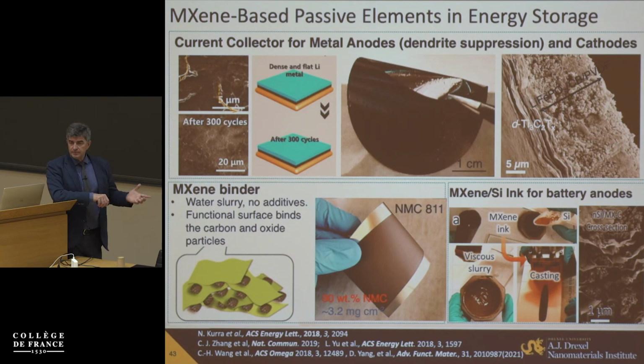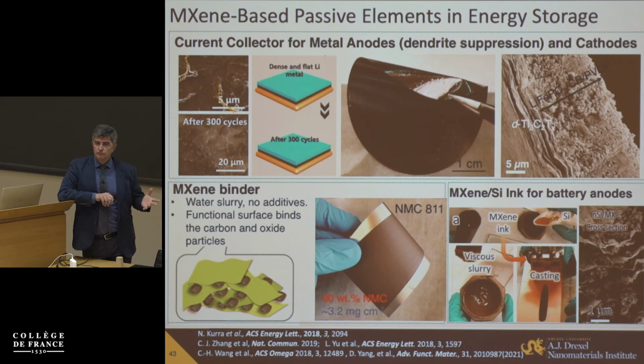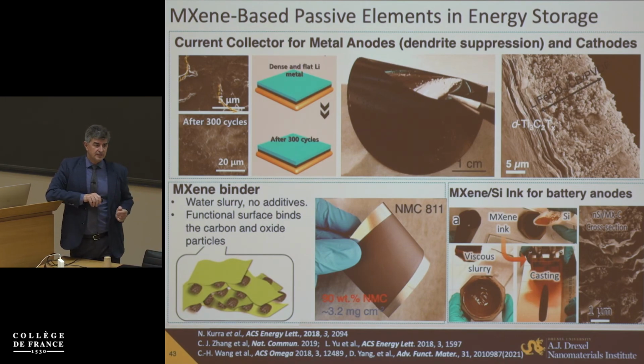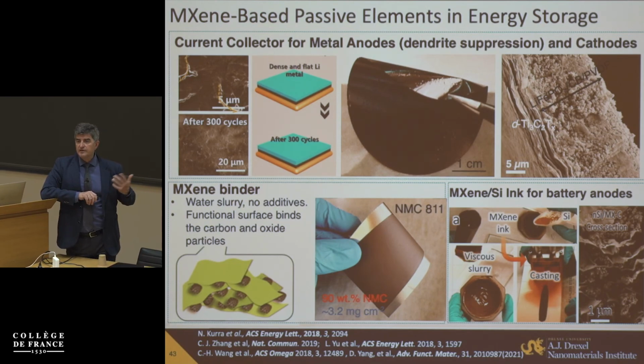But the fact is the fact, for example, lithium, sodium, potassium have been shown to grow pretty much dendrite-free. At least, again, this is a tricky area for testing, but at least in conditions tested so far. So there is promise definitely for current collectors for metal batteries here, decreasing the weight, and also MXene, as you have heard, can work safely with chloride electrolytes. So we can reach out into a range of electrolytes, including material where conventional metal current collectors cannot work here.